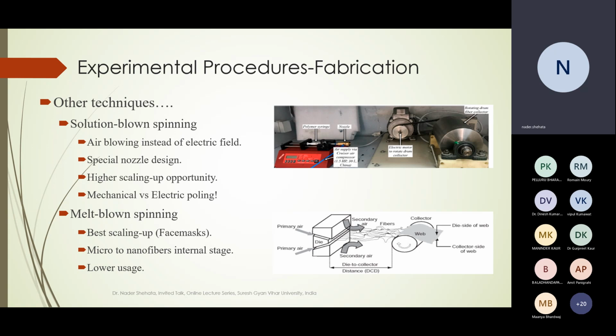However, it has some drawbacks, such as special nozzle design. Most likely you will need to redesign the nozzle according to the polymer or the organic solvent used, in addition to the trade-off between mechanical pulling and electric pulling, because in some piezoelectric nanofibers, the electric field would be much more effective in reorientation of electric dipoles and consequently enhancing the piezoelectric efficiency compared to the mechanical effect of the air pressure. So each technique, as I'm saying, has some pros and cons depending on your choice.